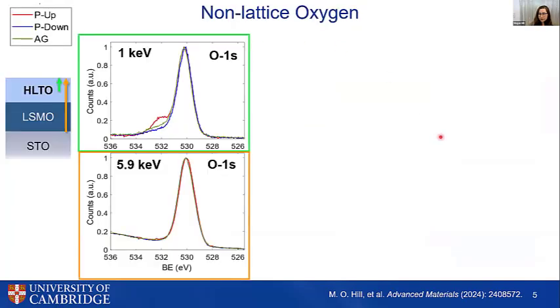So just to get into some of the results, first looking at the oxygen 1s spectra for HLTO. This is at 1 keV and 5.9 keV. And the most obvious feature we can see here is that comparing between the P up, which is red, and then P down and as grown, we see this peak arise at 532 eV.